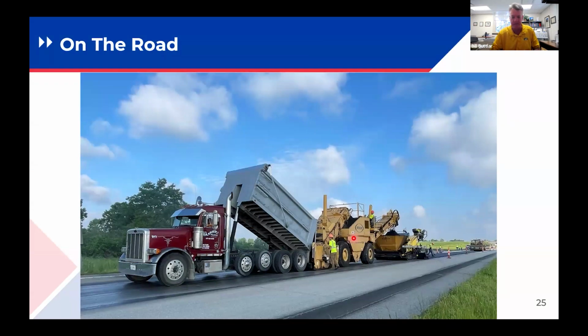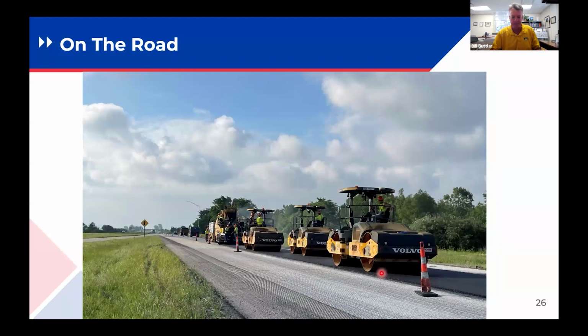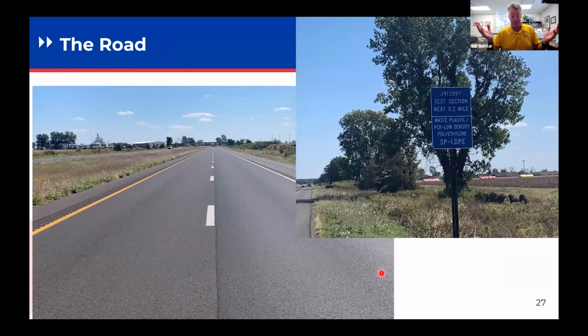Great if you can use a shuttle buggy, obviously, to reduce thermal and material segregation. Always great practice, but kind of the temperatures of production and the materials you use, the paving train is essentially the same for the rubber and the plastic. So you can see breakdown, intermediate rollers there on the Interstate I-55 eastbound. It looks like asphalt while you're making it in the lab and in the field. You can smell the rubber a little bit more, you can't really smell the plastic, but it's otherwise just kind of business as usual.